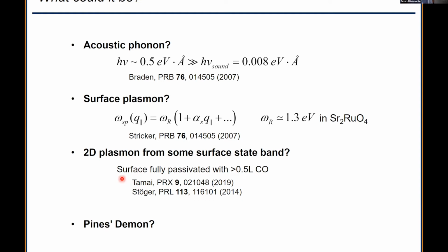And it turns out if you fully passivate the surface of strontium ruthenate with carbon monoxide, which is in every ultra-high vacuum system, all the surface bonds get terminated and the surface states go away, and you get essentially the bulk Fermi surface. This is actually highly studied by STM and ARPES groups, and we expose the system to at least 0.5 Langmuir of CO, which is orders of magnitude more than is needed to passivate the surface state. So there aren't really any conventional explanations for what this mode could be.